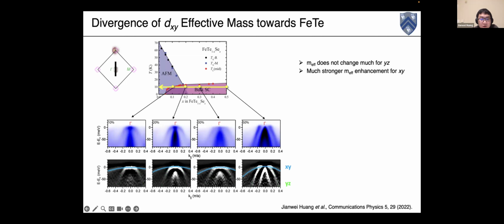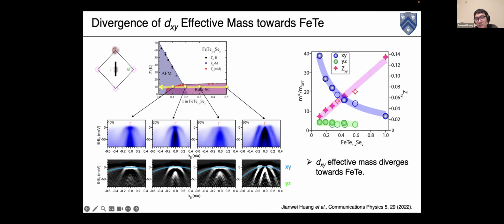We can actually fit those band dispersions by the parabolic band and extract the effective mass, and the blue circles are the extracted data. We find that the effective mass actually diverges towards this iron tellurium compound, and we can just take the inverse of this effective mass, which is equivalent to the quasi-particle spectral weight, and it linearly extrapolates to zero very close to the iron tellurium region. So this strongly suggests that iron tellurium is in, or at least is in proximity to, the orbital-selective Mott ground state.